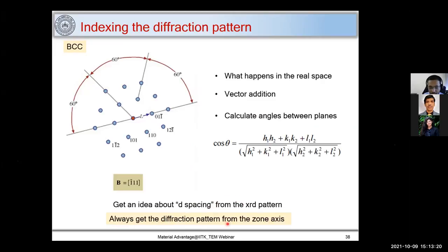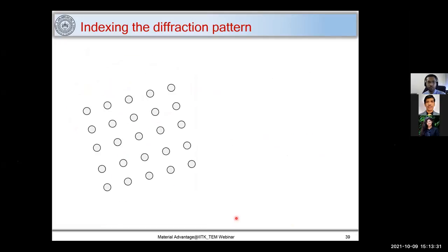And always get the diffraction from the zone axis. What do I mean by that? Your pattern should be symmetric; it should not be somewhere you are out of the zone. Now let's consider this random pattern. If you want to index this, just take the shortest reciprocal points from the transmitted spot and make them D1 and D2. Mark D1 and D2 and find them by measuring these distances.